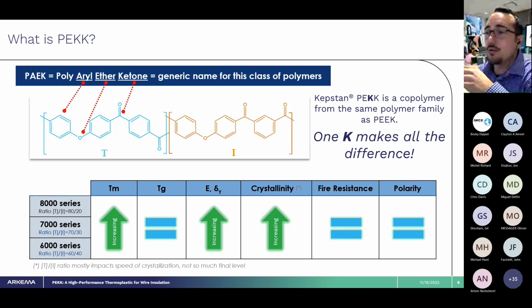So as you approach more of a 1-to-1 ratio, you'll actually lower the crystallization rate and also lower the melt temperature. This opens up a window of processing which isn't achievable with some of the other PAEK materials, especially with such a high ketone content.